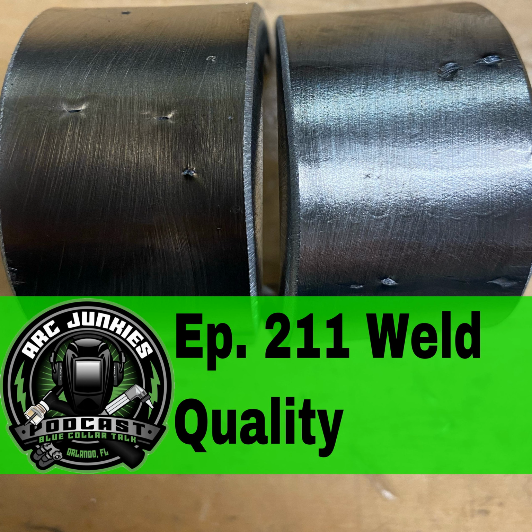Take the time and clean the slag out of your material, because essentially what you're doing is you've got slag in there, you weld over top of it, now you've covered it up. You just can't see it. It doesn't mean that it went away. And if they do RT or X-ray on here, or they do a guided bend test, it's going to rear its ugly head and you're going to see it again. But the best thing to do is just make sure you clean all of the slag out.